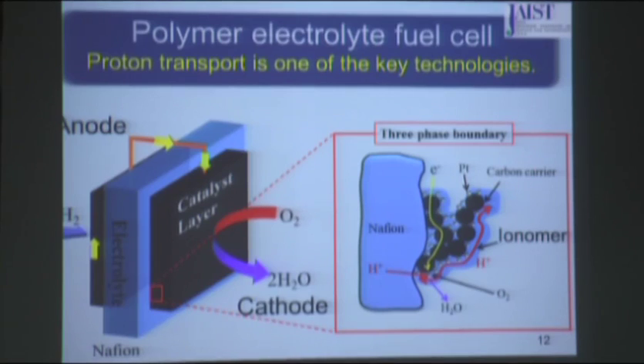So the hydrogen reacts on the surface of that black catalyst layer, then produces the proton. Today's talk is about the proton, which is very important. The proton can be transported to this blue region, the electrolyte. This is the membrane, which completely separates oxygen and hydrogen. Then the proton is transported to the cathode side, then meets the oxygen on the platinum surface. That is the electrocatalyst. Then it produces the water.